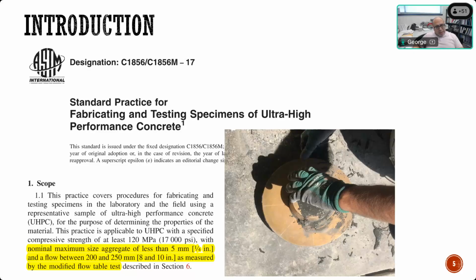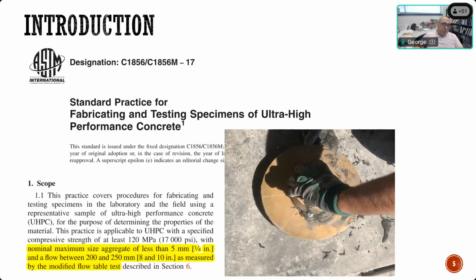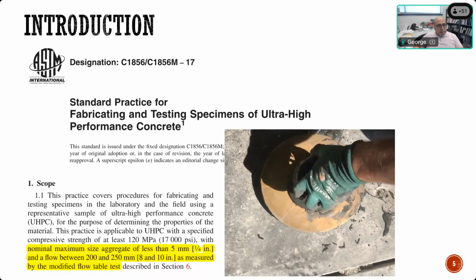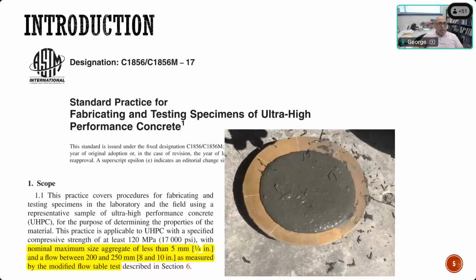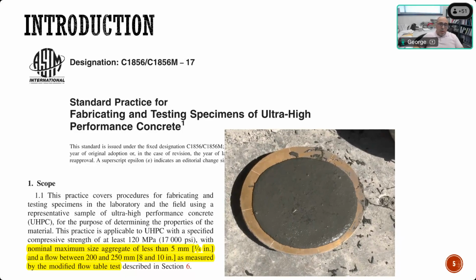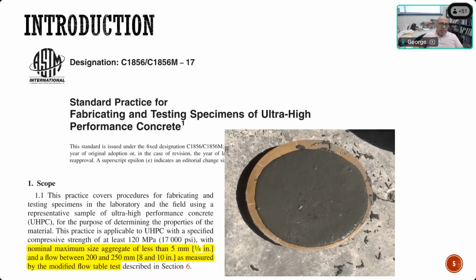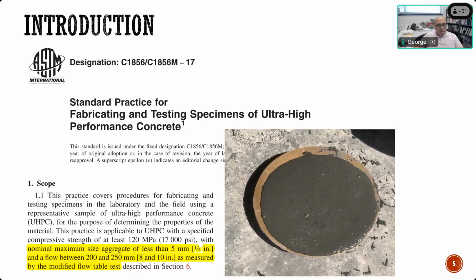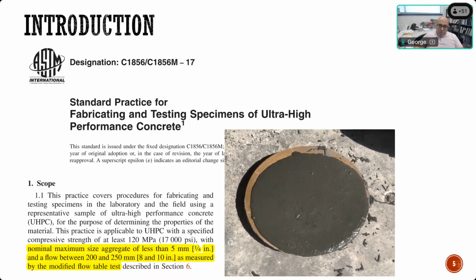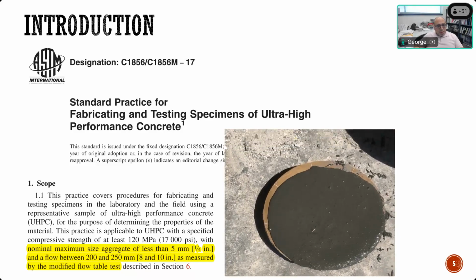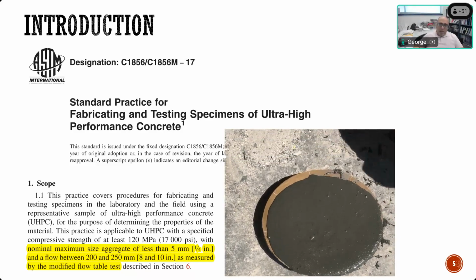It also adds a statement that is not in the FHWA definition, which is having a flow from 8 to 10 inches, measured using the flow table test that I show on the screen here. So it's a very flowable material. It's like a self-consolidating concrete type of material, so you don't need to vibrate it. You also gain the ability for this material to flow and fill very tight spaces between reinforcement or strand, or require very small cover, because it's highly durable, and at the same time it is also very flowable.